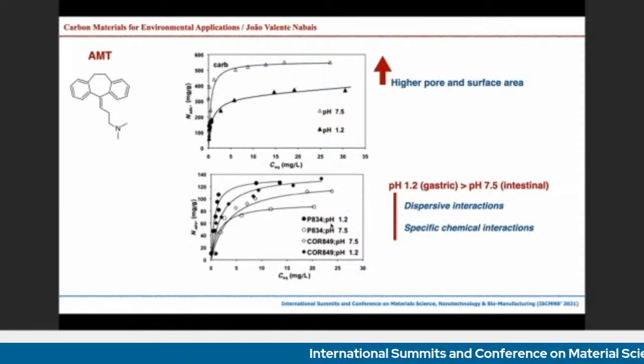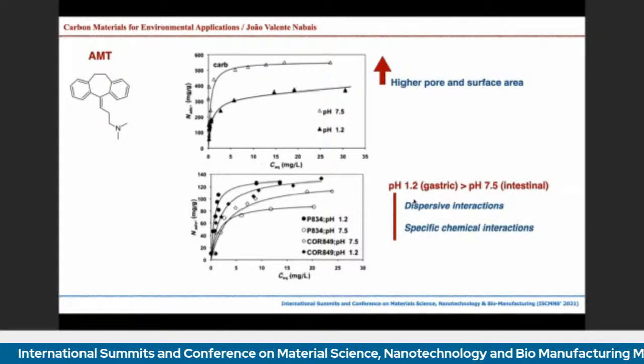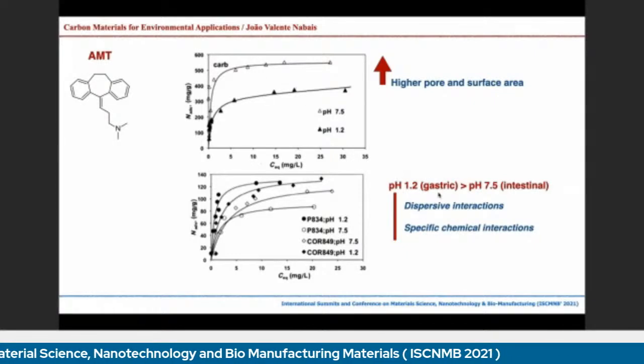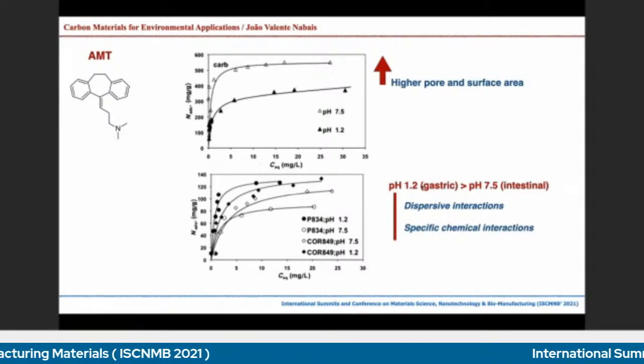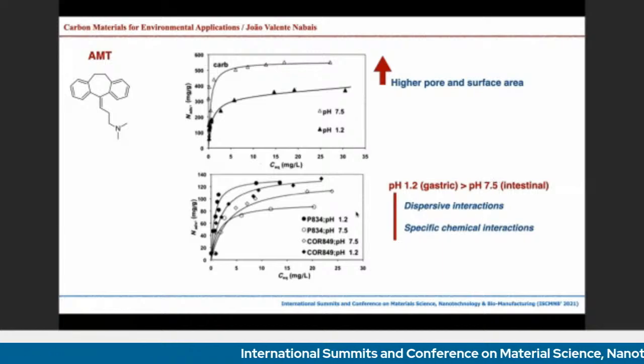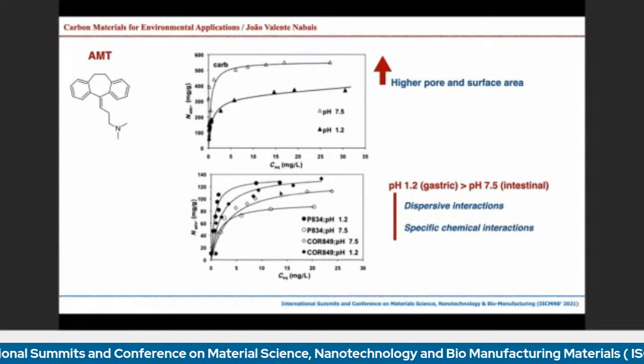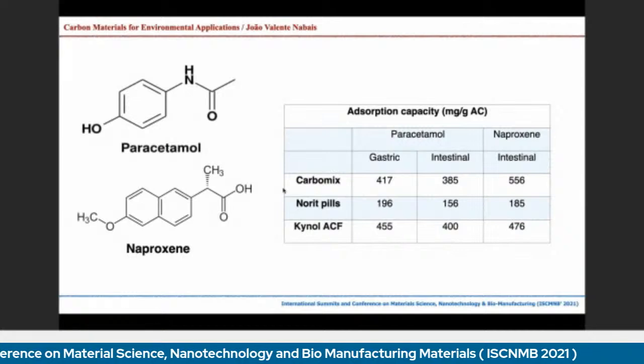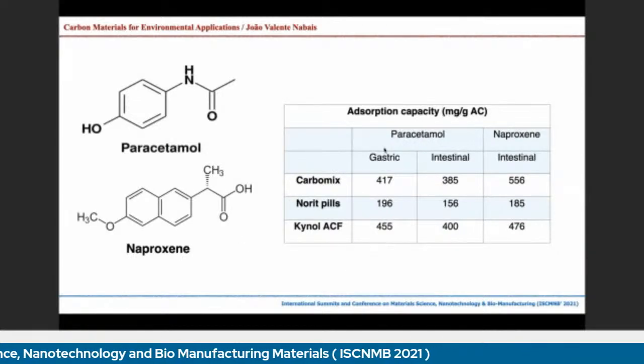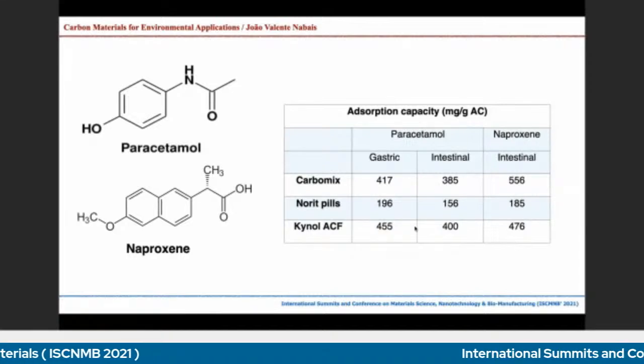So when it comes to our materials, what was quite interesting to see is that our materials are different from the Carbomix. They are absorbing more AMT under the gastric conditions than at pH 7.5, which is regulated by dispersive interactions and specific chemical interactions again. When it comes to paracetamol and naproxen, again, you can see here the amount absorbed, which is quite interesting.